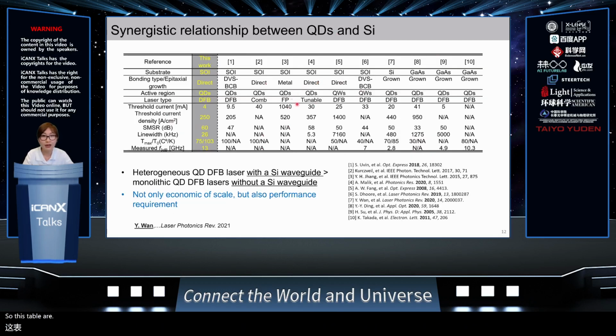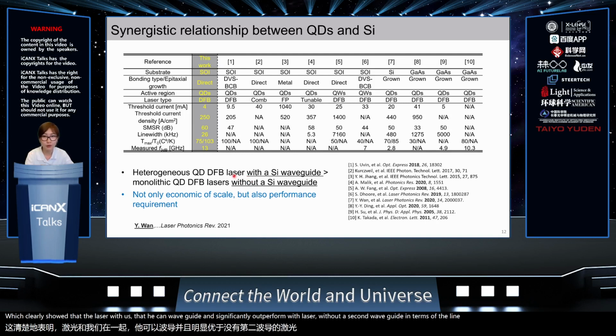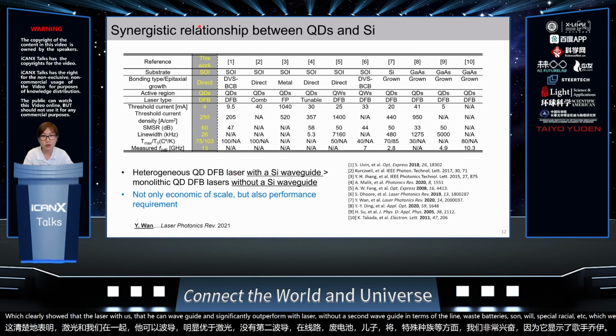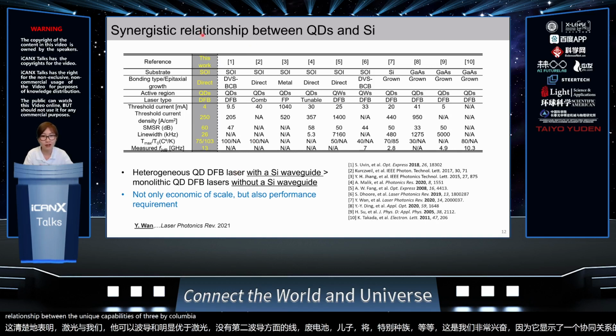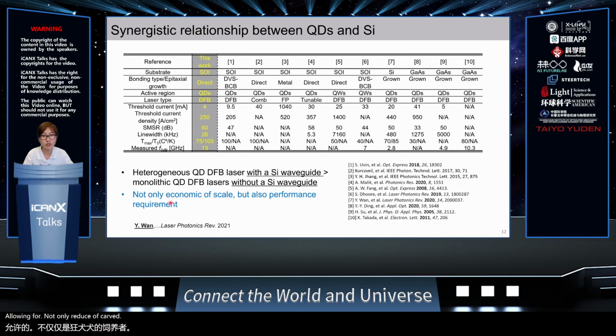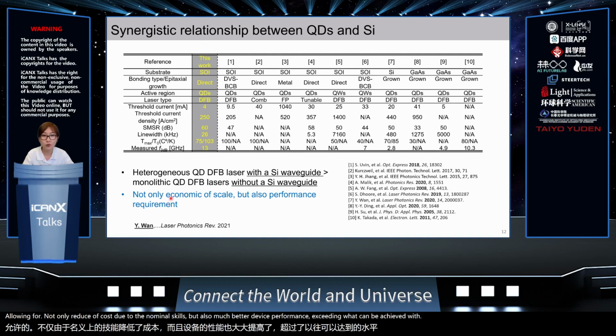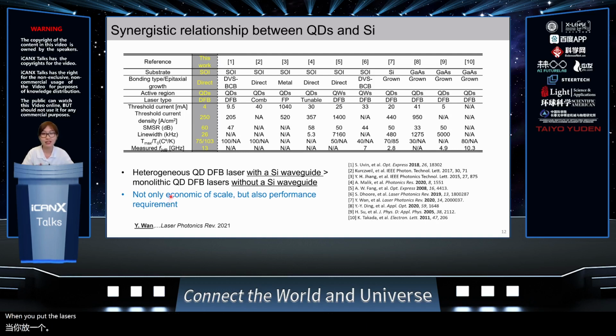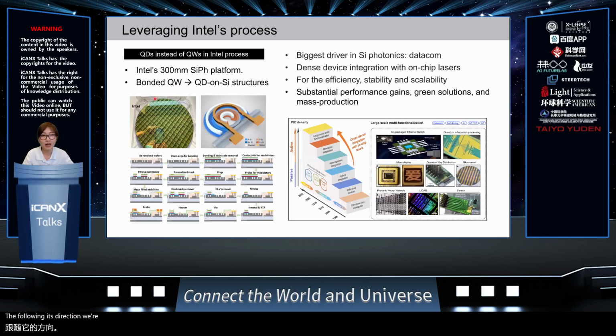So this table compares the device performance of this work and the previously reported work, which clearly shows that the laser with the silicon waveguide can significantly outperform the laser without a silicon waveguide in terms of linewidth, bandwidth, side-mode suppression ratio, etc., which we are very excited about, as it shows a synergistic relationship between the unique capabilities of III-V quantum dots and silicon, allowing for not only a reduction of cost due to the economy of scale, but also much better device performance, exceeding what can be achieved with purely III-V quantum dot devices. So when you put the lasers on silicon, you not only get a better substrate, you also get better lasers.